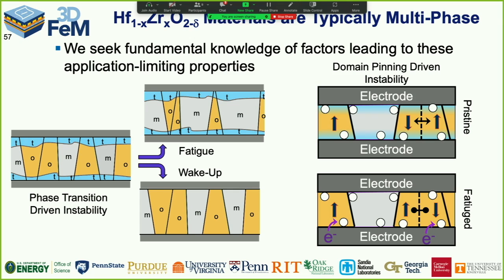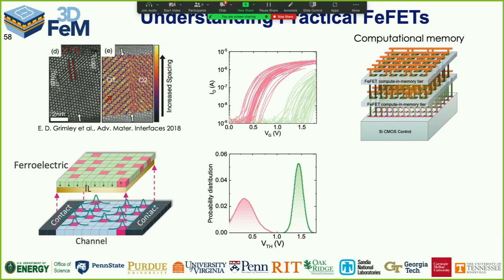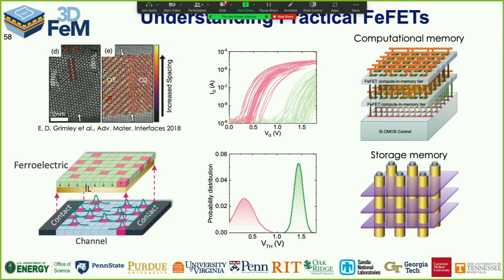Solid state ionics, which means oxygen vacancies move in these materials, is the primary failure mechanism for most electroceramics. And it also turns out to be what turns the ferroelectricity on and off in these materials. It's a little bit scary as a material system to work with because of that. Because if I don't get the oxygen vacancy concentration right and fixed in the material, they'll wander as I apply electric fields. And so among the things that we're working super hard on is to try and understand in real scale devices from GlobalFoundries exactly how you turn these materials on and off.